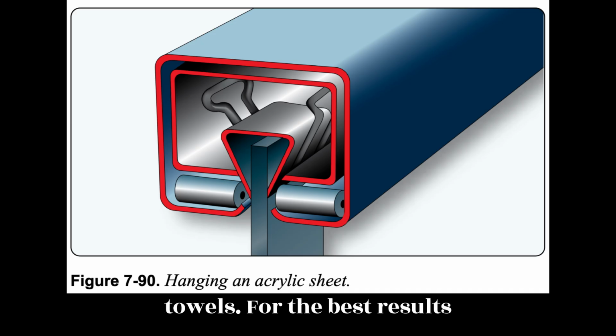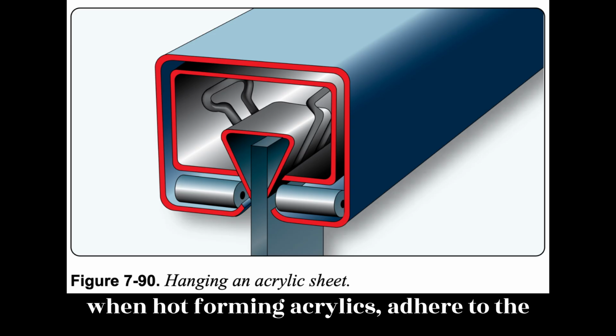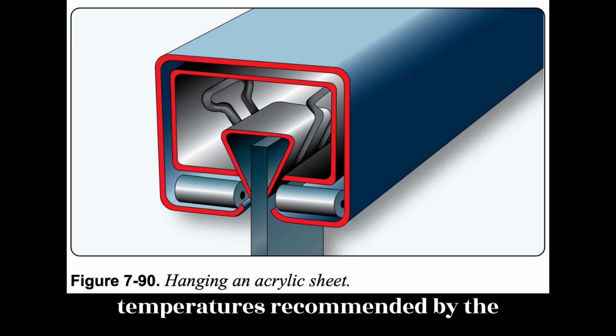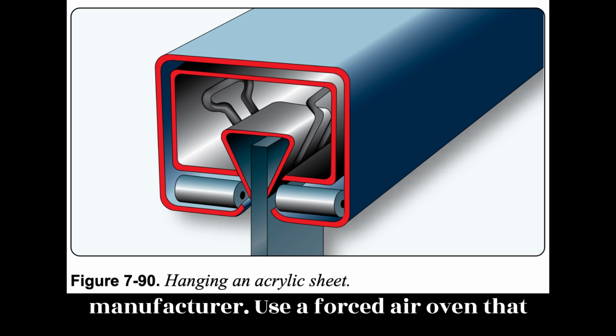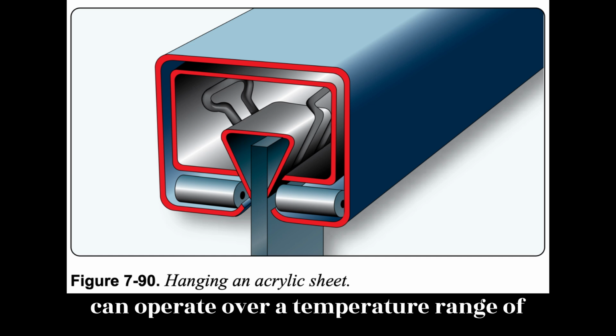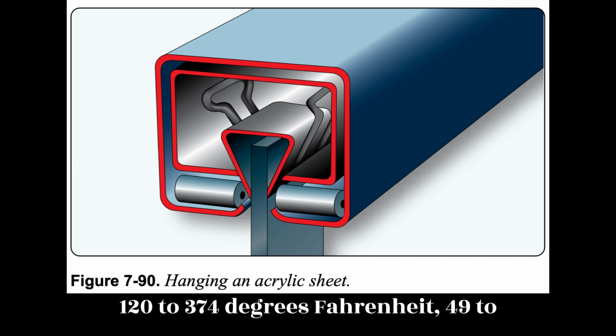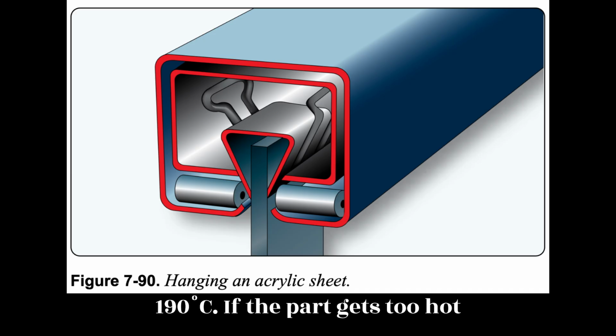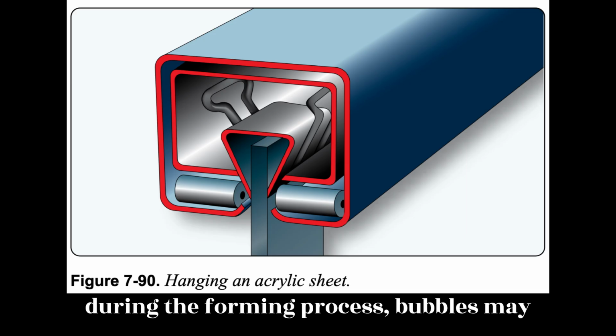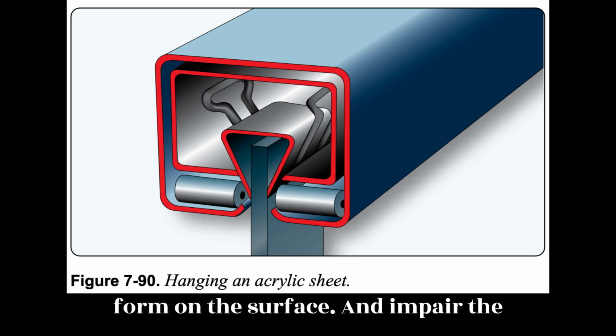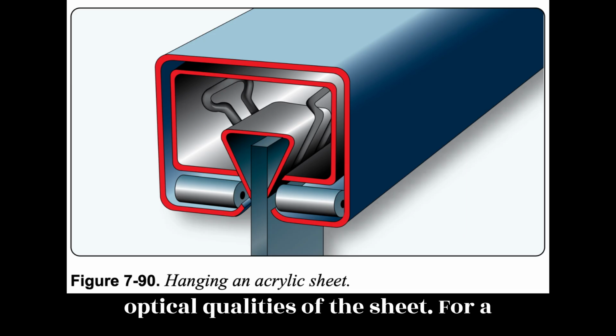For the best results when hot forming acrylics, adhere to the temperatures recommended by the manufacturer. Use a forced air oven that can operate over a temperature range of 120 to 374 degrees Fahrenheit, 49 to 190 degrees Celsius. If the part gets too hot during the forming process, bubbles may form on the surface and impair the optical qualities of the sheet.